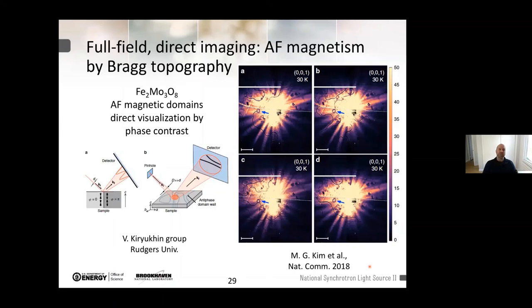What is instead published is that out of an experiment that we did with V. Kiryukhin group from Rutgers University, we noticed that apart from the very strong signal coming from the center of our detector, hidden by our beam stop, and this white line and white dot here, all the field that is hitting our sample out of our pinhole, in this case we use the pinhole, can actually bring relevant information. So this is a specific sample kept below its magnetic transition temperature on the magnetic propagation vector.